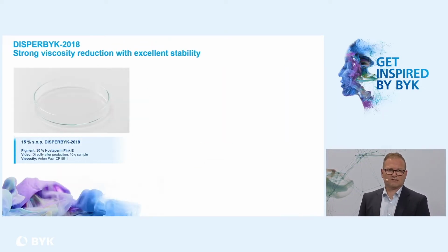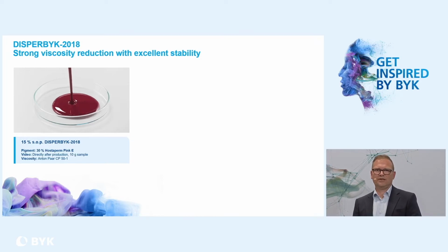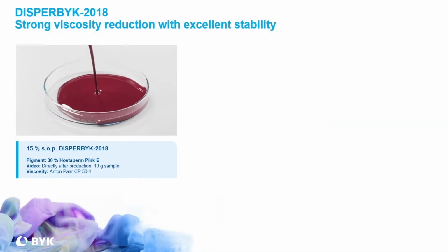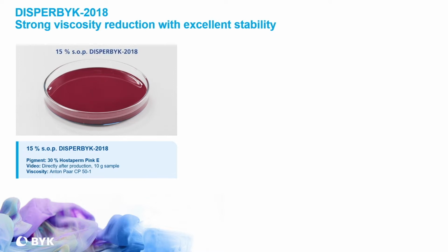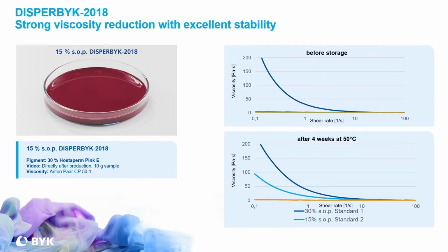Coming to some results with Disperbyk 2018. Here you see a short video about the viscosity reduction, again with an organic red pigment. In this case, Hostaperm Pink E. Very nice flow behavior of the pigment concentrate at a pigment loading of 30%. This was directly after production. But you see here in the graph, the yellow line is Disperbyk 2018. Also after storage, where some other additives failed. So at the beginning, 2 additives in this graph were very good, but after the storage, they differentiate. Just Disperbyk 2018 gave also after storage the good performance, the low Newtonian flow behavior.